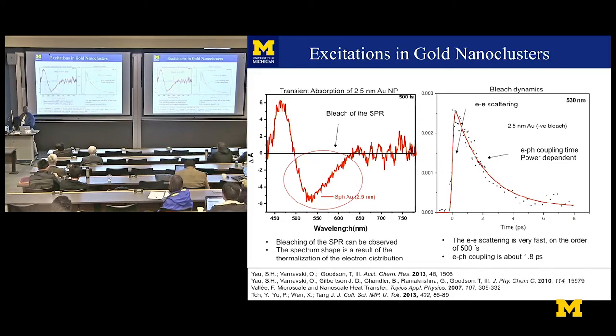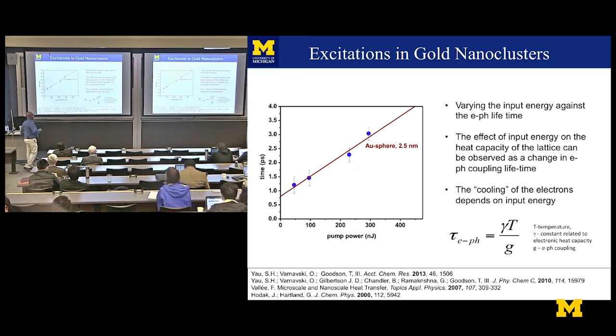Just a typical case. And within a typical case for the big particles, what you could do is just increase the power. You turn up the juice, you increase the number of photons, you increase the temperature, right? And if you increase the temperature, the time takes longer to decay, right? Okay, and so you can use some simple model then for the cooling of that electron-phonon relaxation in the big particle that is related to the temperature divided by some coupling constant. And then the proportionality, of course, is the heat capacity. This is basic thermodynamics, okay? So big particles behave like you would expect. You heat them up with photons, they absorb the photons, and if you increase the temperature, the time for the cooling of those vibrations and the couplings takes longer, and you can use the heat capacity just to measure that.